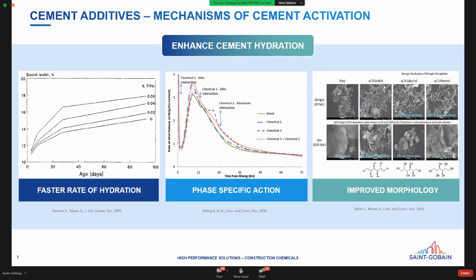A denser hydrate network decreases the porosity at the mortar and concrete level. Consequently, the mechanical strength is enhanced. The mechanism shown focused on the clinker phases, but activators play on some SCM phases in a similar way. Indeed, we can assume that fly ash, being a porous material, will also actively participate in the matrix densification if its hydration process is enhanced.